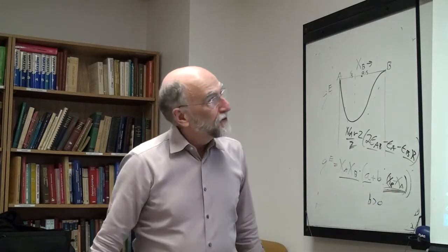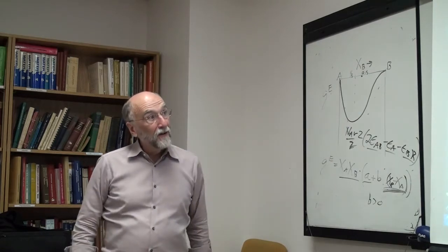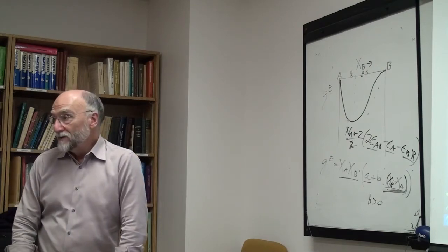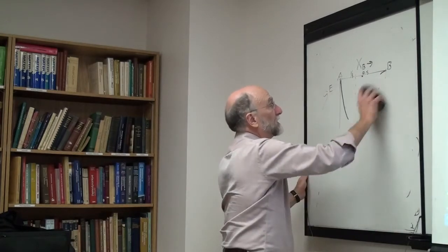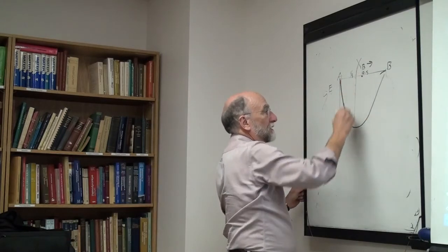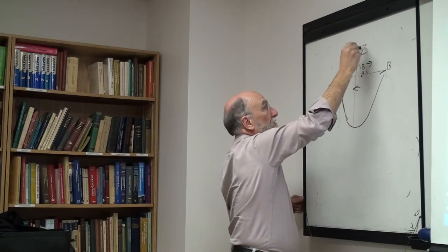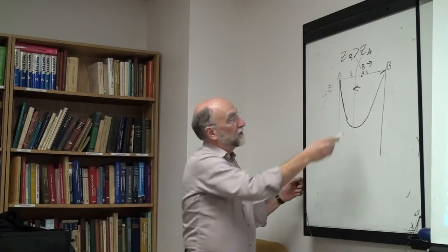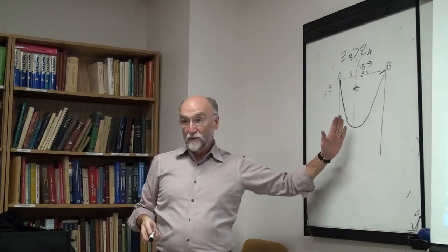But we see there's another reason that the minimum can be shifted. The minimum can be shifted, at least in a liquid here, I'm not talking about a solid, because of change of coordination number. Okay, so supposing that the bond energies remain more or less constant, and now we're talking about a liquid, the reason this shifts over to this side is because ZB is greater than ZA. And if ZB is greater than ZA, the minimum will tend to be on the side in which you have more A's around B's and B's around A's, so you're going to shift the minimum.